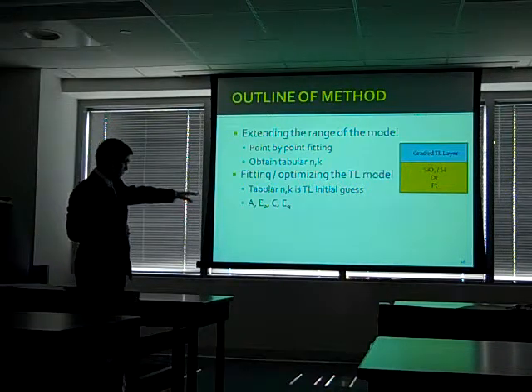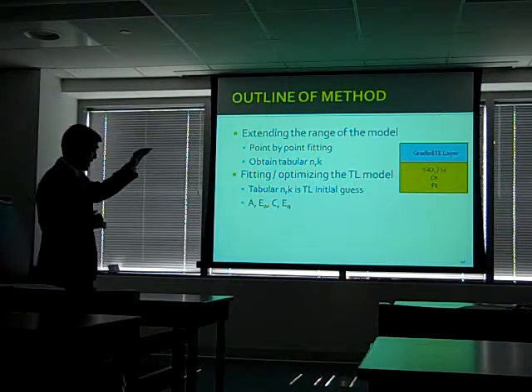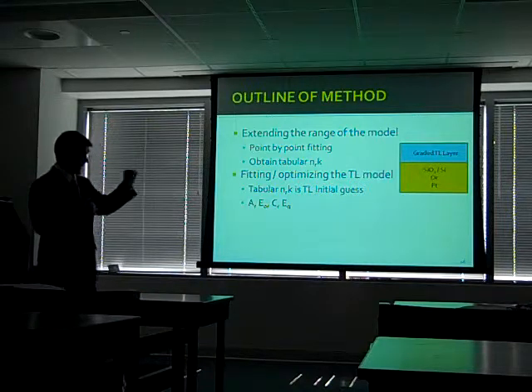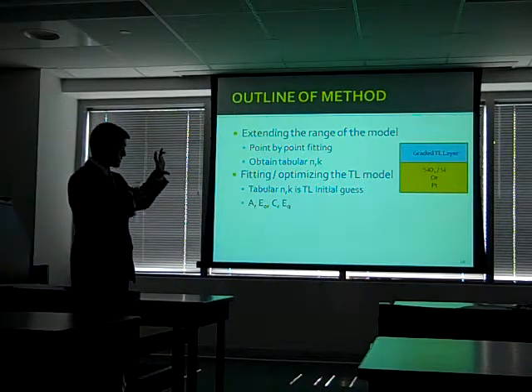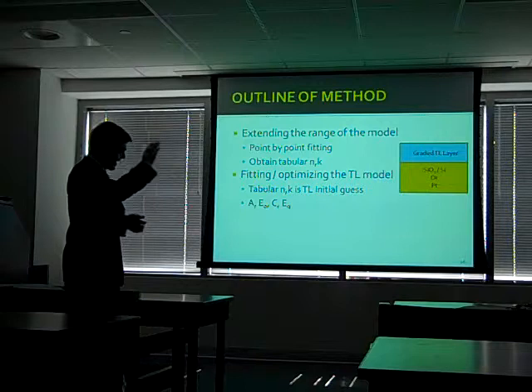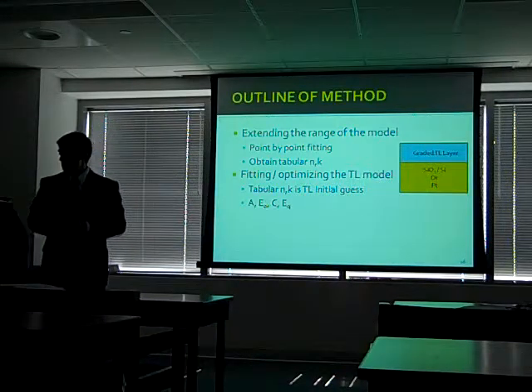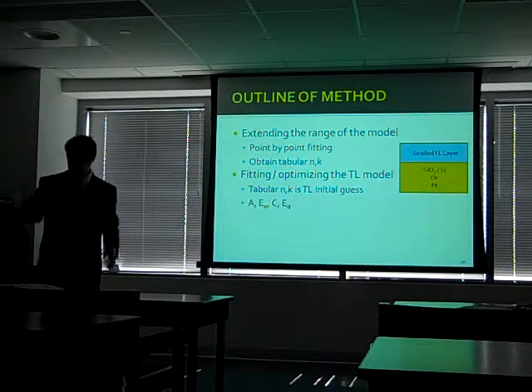So we fit the free parameters of the Tauc-Lorentz model to that spectrum, and then make a graded Tauc-Lorentz layer on top of your substrate and run the optimization. So then the result would be optimized optical constants.